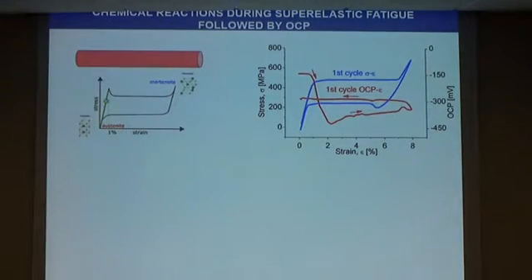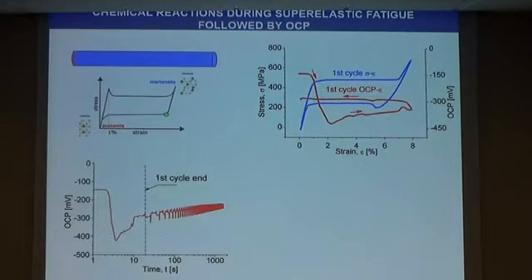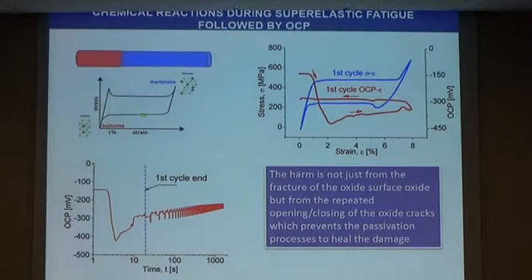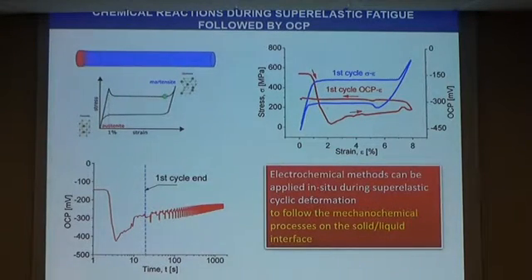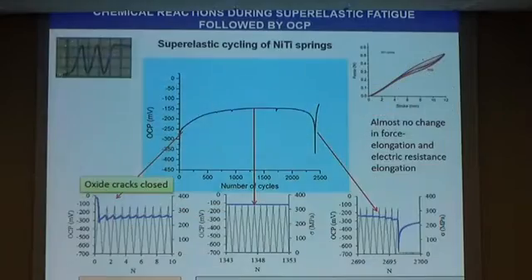If you do it repeatedly in one cycle, this is how the response looks. This is the superelastic curve, and this is the response of the OCP. Fracture, and then some kind of recovery. I already showed this figure, and I would like to emphasize that the harm is not from fracturing the oxide. The harm is from periodically opening, closing, and the hydrogen production inside. These electrochemical methods can follow what's happening on the surface.